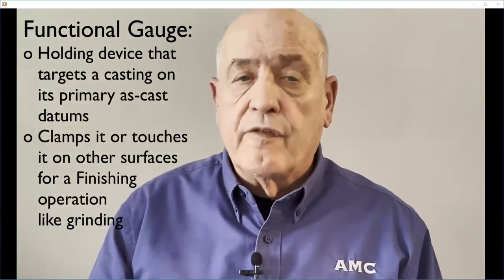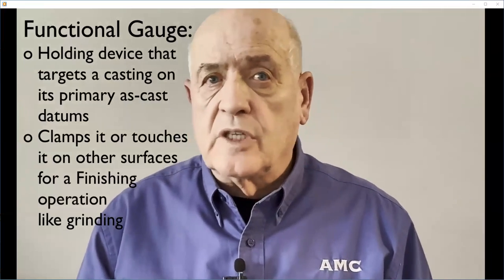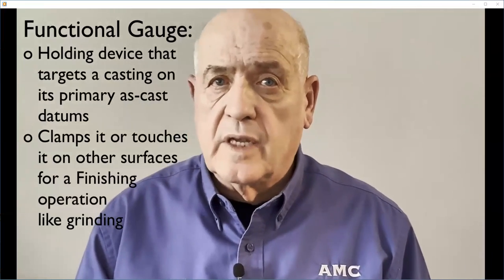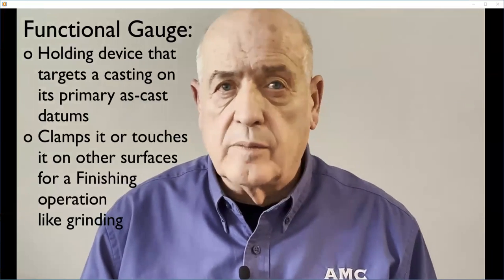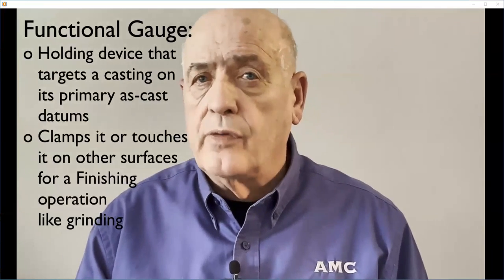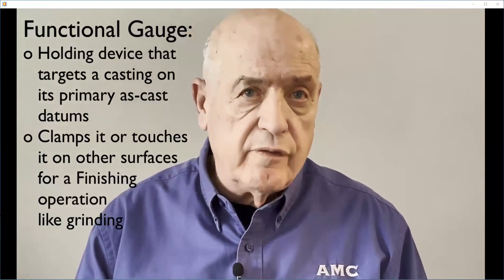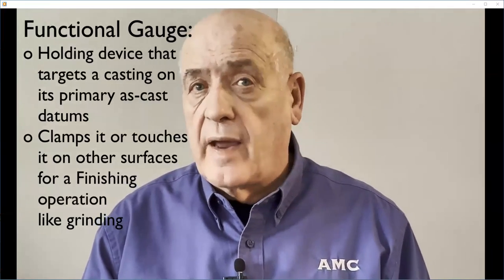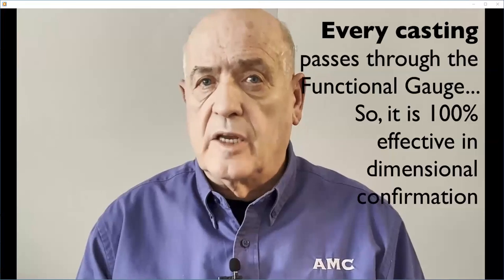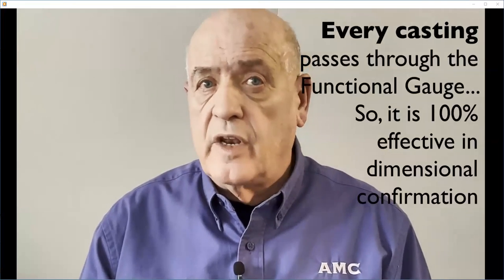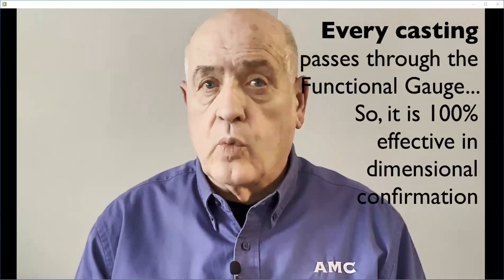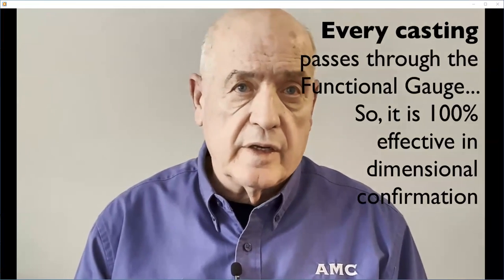A very effective tool for protecting the as-cast features that are most important for casting machining setup and as-cast features used in final assembly is a functional gauge. A functional gauge is a finishing process holding device that targets a casting on its primary datums and clamps or touches it on other surfaces important to the first machining fixture and/or as-cast final assembly features. Every casting passes through the functional gauge in its finishing process step. Therefore, it's 100% dimensionally effective.